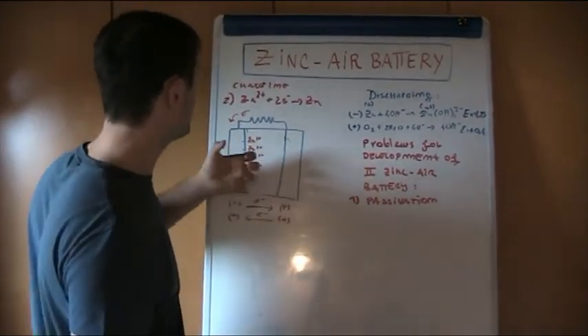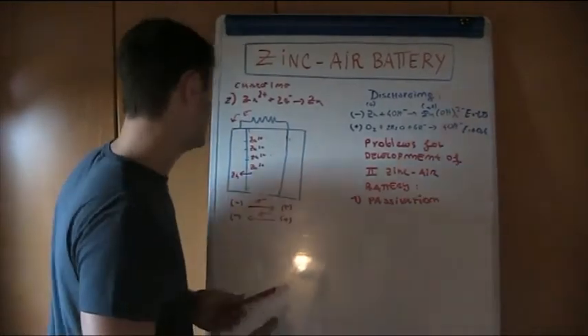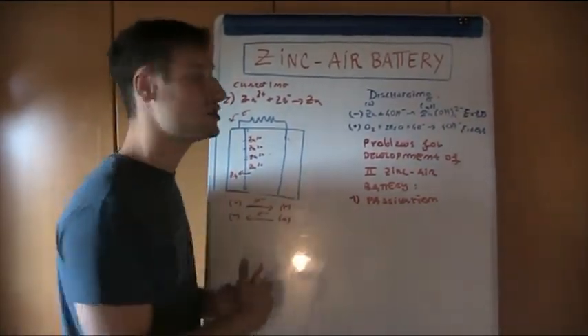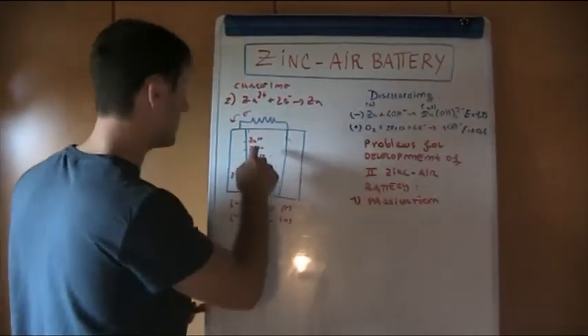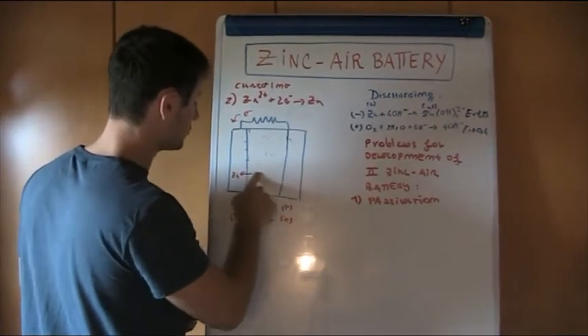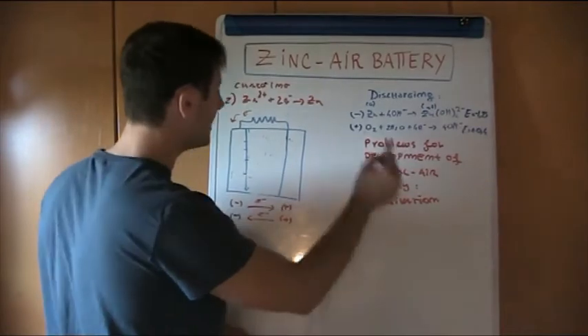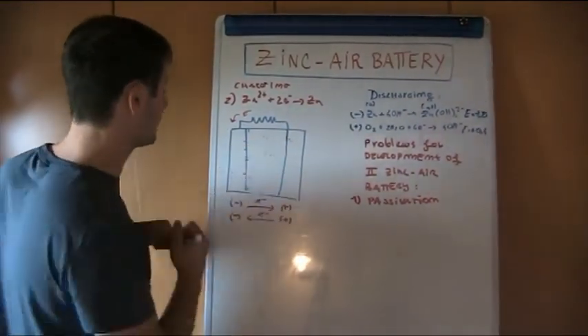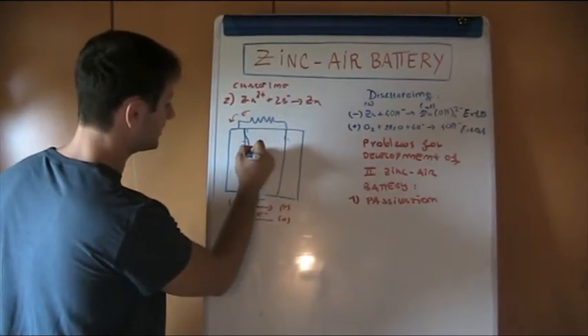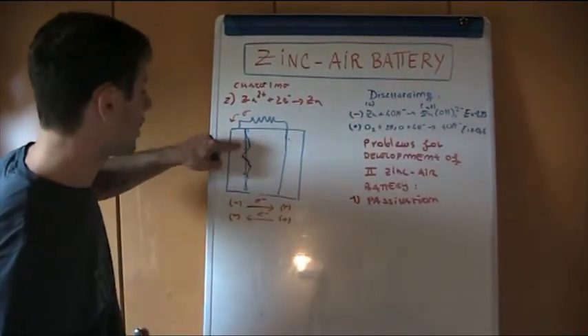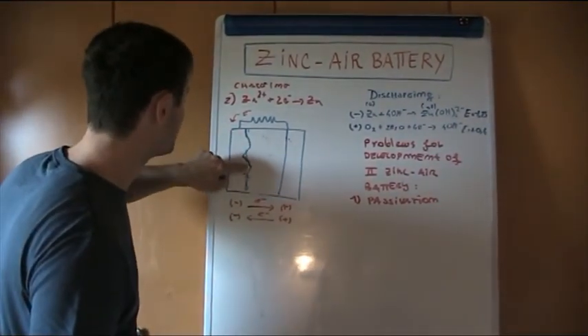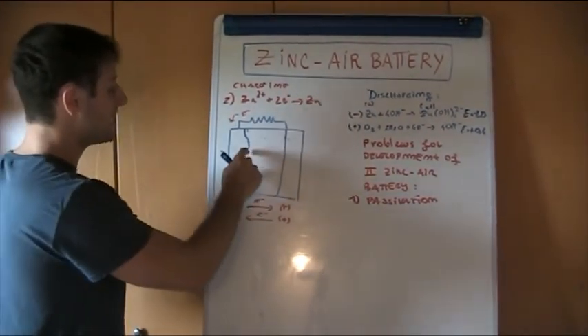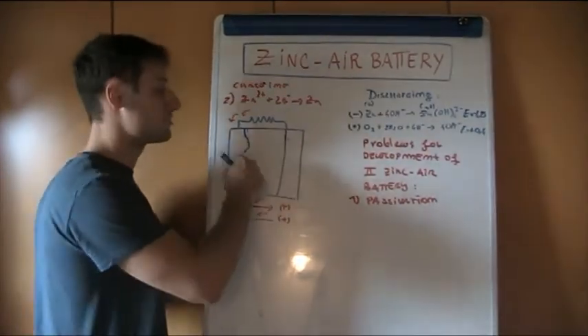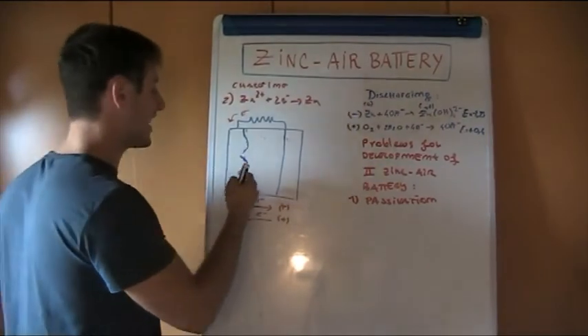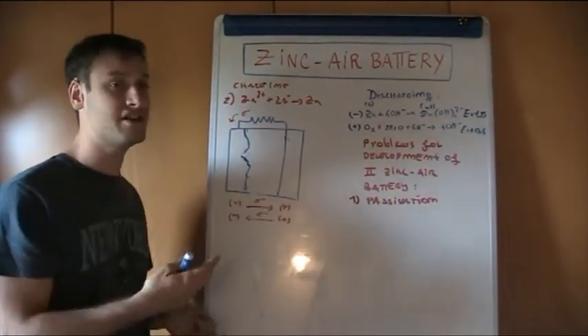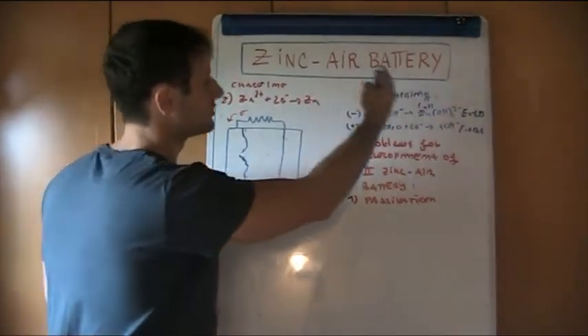Whereas when we are regenerating the zinc due to the applying of a potential, it's not so obvious that the redeposition is completely homogeneous in each point. And so maybe at the very beginning we can have a flat and homogeneous surface, but later when we want to regenerate the substrate, maybe some zinc 2+ prefer to arrive here, a little bit less here, maybe a little bit more here, and we are basically losing the homogeneous shape and the smooth shape of before. We are creating a change in morphology, and this is a problem for the performance of the battery, because since we are modifying and decreasing the homogeneity of the electrode, the DDP decreases and the final performance decreases when we are running a further discharging process later.